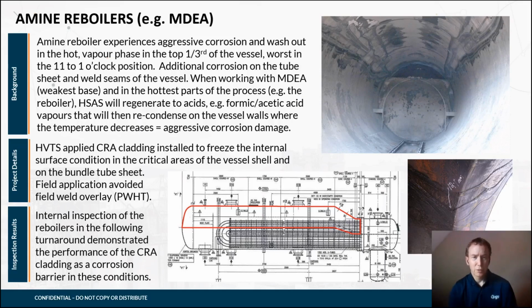Again, installing a high velocity thermal spray system here will stop that corrosion activity taking place. It also has very good abrasion erosion resistance, so will resist the abrasion activity from the turbulent flow. So provide a long-term solution in these environments.